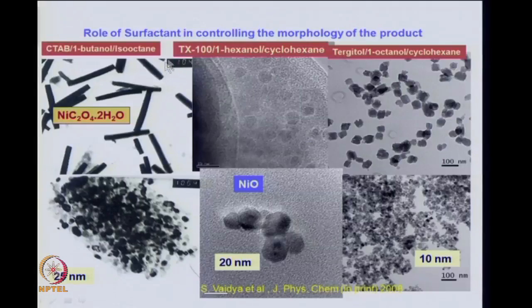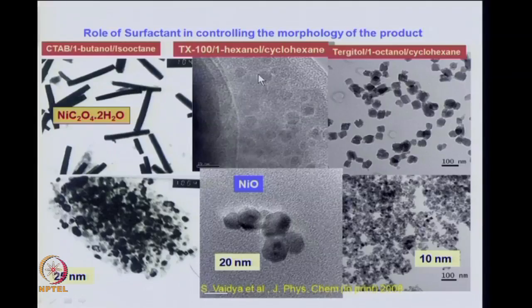This is another case where the surfactant we have changed from cationic surfactant. We always get rods as we discussed in the previous slides. If you change the cationic surfactant to TX100, this is called Triton X100, it is a neutral surfactant of some molecular weight, some size, we get spherical particles, not rods like you get in cationic surfactants. This is nickel oxalate dihydrate. In all the cases, you will get same X-ray diffraction pattern telling you all of them are nickel oxalate dihydrates, but when you look at them, some of them are rod like, some of them are spherical particles, and some of them have cube like shapes.